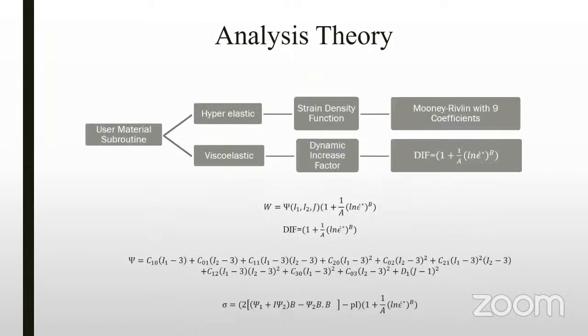In the present study, I have tried to simulate both the hyperelastic and viscoelastic behavior of this material by writing the user material subroutine linked to the Abaqus software. In this subroutine, I use the strain energy density function of Mooney-Rivlin with 9 coefficients to predict better and more accurate hyperelastic behavior of this material. And to simulate the viscoelastic behavior, I have used the dynamic increase factor multiplied to the strain energy density function to make a hyper-viscoelastic density function.